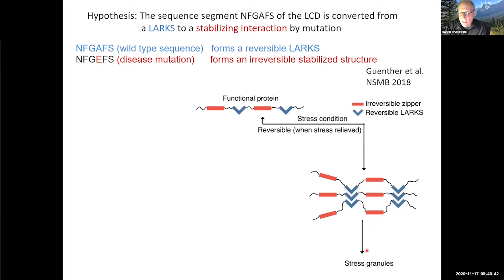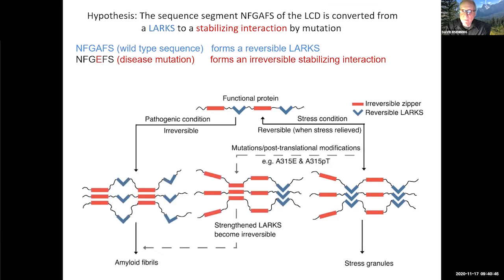But under other conditions, one is mutation, another is phosphorylation, then these LARKS can be converted to sequences which form steric zipper-like structures, and we get irreversible fibers rather than reversible ones. And still, there are other conditions like extremely high concentration. We can drive these proteins from reversible to irreversible conditions. So that's our thinking on this conversion.